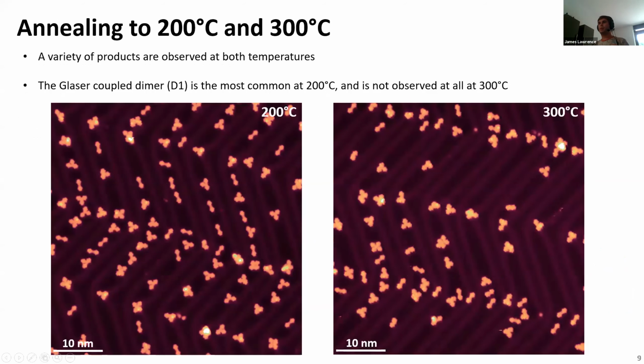samples. So as you can see, there's lots of different species on the surface. There's various dimers, some trimers, and even some tetramers here. So obviously there's probably quite a lot of different linkages between these pyrenes, which if we use STS and dI/dV spectra and mapping, we can understand their electronic properties. So even if it's not a particularly selective reaction, this is still good for us in a way.